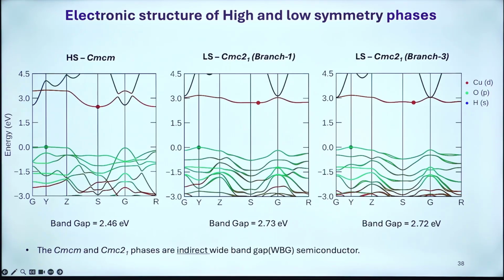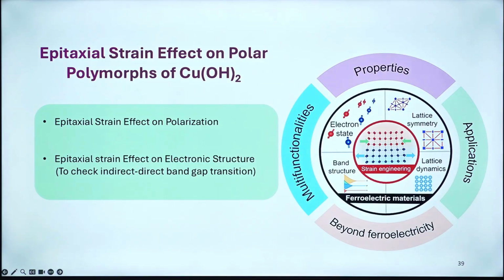That's what we conclude. Then what will happen to the strain? So now I identified a potential ferroelectric phase. Now what will happen if I try to apply strain on this particular system? Whether the strain can do some wonders, because this is to complement the experiment, because they always have a substrate which will have a strain on the real material, the thin film which they deposit, like strontium titanate substrates. So now we are trying to mimic indirectly the same substrate strain on the lattice.